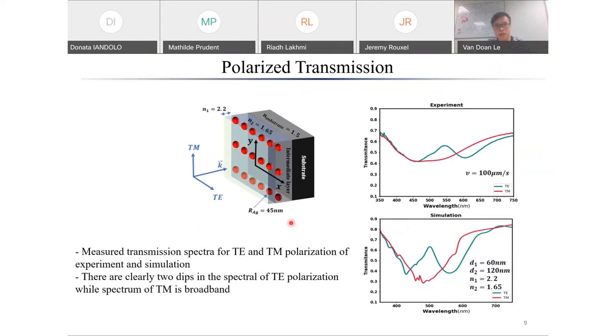And the second part is the polarized transmission of the sample, which is the anisotropic property of the sample caused by the self-organized nanoparticle grating. Here is the transmission in TE and TM, experimental and simulation. You can see a huge difference between TE and TM. In TE polarization, you can observe two dips and one peak. There may be two optical mechanisms coupled together. And in TM, there is a broad dip.